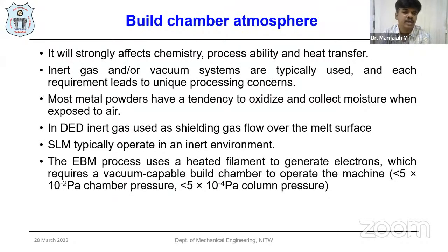Even in DED, we are using inert gas as a shielding gas flow over the melt surface to avoid oxidation or creating defects. Even SLM typically operates in inert environmental conditions, either argon, helium, or even nitrogen.